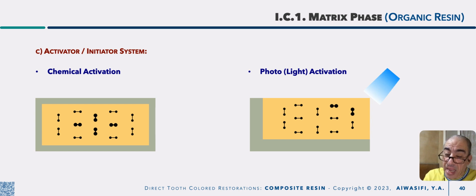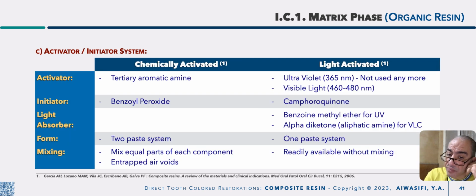It will not be cured or start the reaction unless you expose it to your light curing device, but it will absorb a small amount of ambient light from time to time. If you repeatedly use it without recapping the tube, it will absorb a cumulative amount of light energy that will affect its shelf life, and it may self-decompose and the material will set.